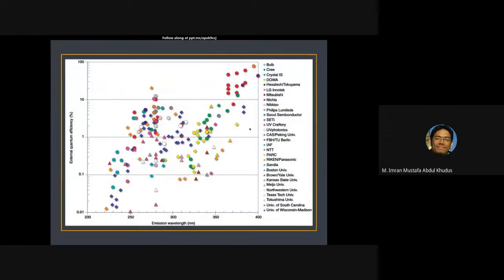Okay, so this is just a graph of what has been achieved, right? This is the newest one, and this is the best one in the region that we are most interested in. These ones, you can see here, the ones above 10%, a lot of it is just gallium nitride. These ones are aluminium gallium nitride. You can see that most of the effort is actually at 260 nanometers, and thereabouts, 270, 260 nanometers. And this is because this is the wavelength which is most useful for sterilization, right? So really only...